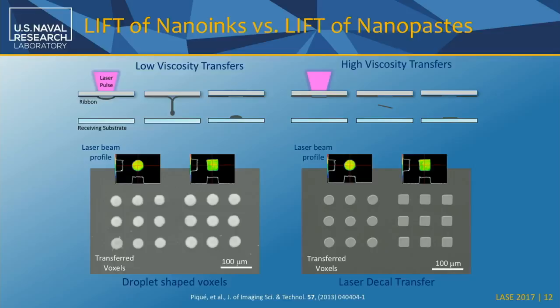We took two silver nano suspensions and transferred them onto a silicon substrate. What I want you to pay attention to is the apertures. This is the laser intensity profile of the beam that is interacting with the donor ink. Here we have a circular aperture, and here a square aperture. The intensities are pretty uniform; we blow up the beam so we get a relatively uniform distribution. It's the same laser and the same conditions. The energy may be slightly different, but we're talking about a small percentage change.